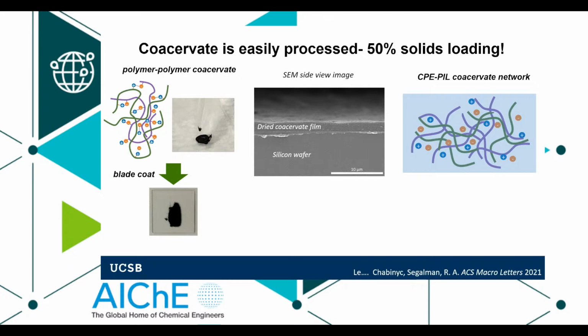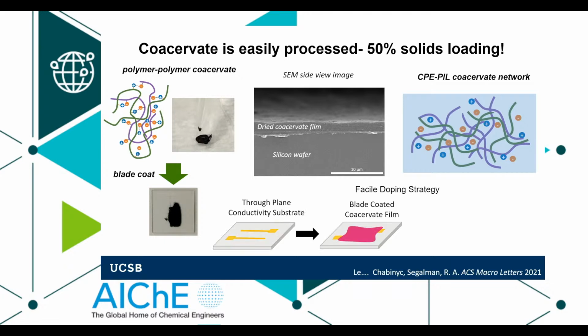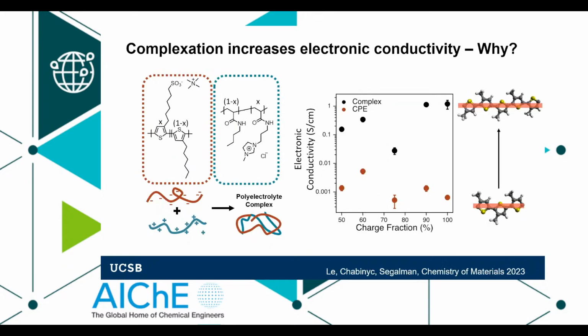We make really nice dense films. They then cross-link together via the ionic interactions. We can do this on top of a substrate, with, for example, electrodes, and dope it and start measuring electrical properties. And the first thing you see is that the bottom red dots are the conjugated polymer from which we made the coacervate. When we form the coacervate, the electrical conductivity goes up by a lot.